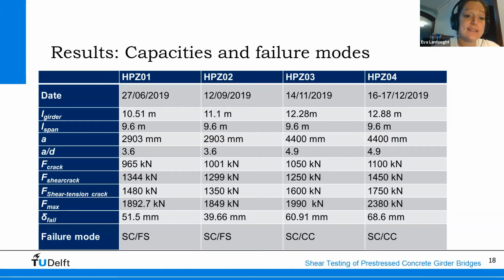A over D distances are outside of the region where we consider typically a direct compressive strut to develop between the load and the support, but our results have shown that there was the development of a compressive strut even at the larger A over D distances.